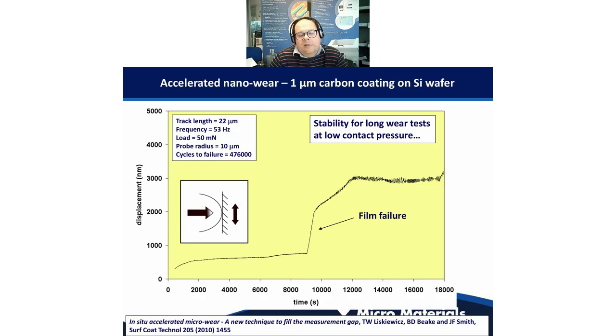So over the first approximately 9,000 seconds, so that's quite a long period of time, in the region of 2.5 hours, we see a sudden increase in the depth of the probe, which corresponds quite well to the 1 micron coating thickness that we're talking about. So at about 9,000 seconds, we get that failure event. And then that stabilizes off, and the contact area has increased a little bit, so the contact pressure will have gone down slightly. And then we're getting what looks like some kind of stick and slip type events in the silicon substrate. So we're building up a lot of failures, and actually it took nearly 500,000 cycles to drive that failure.